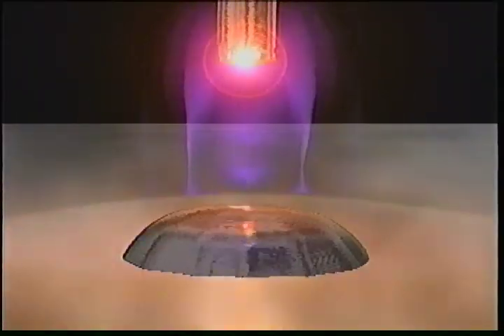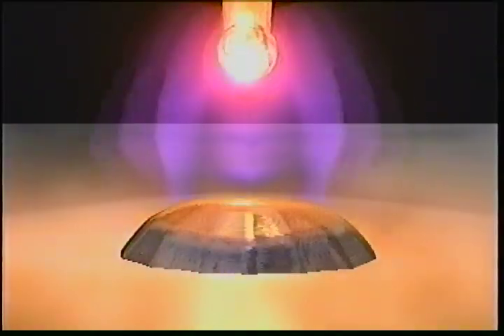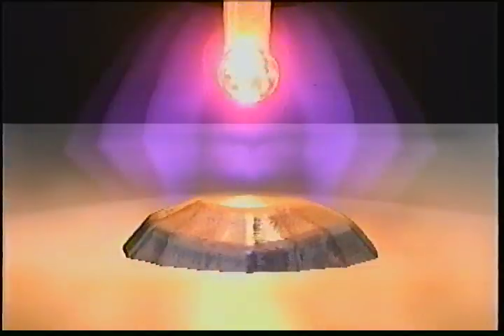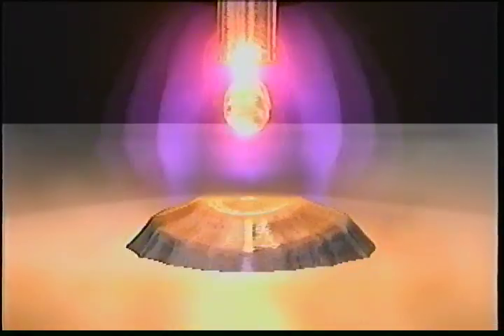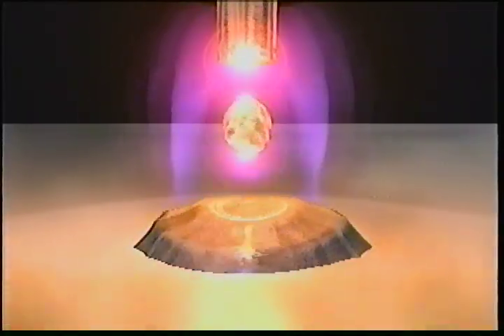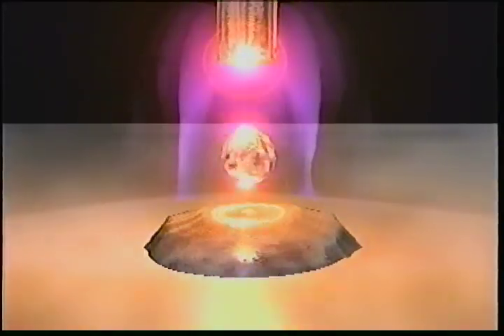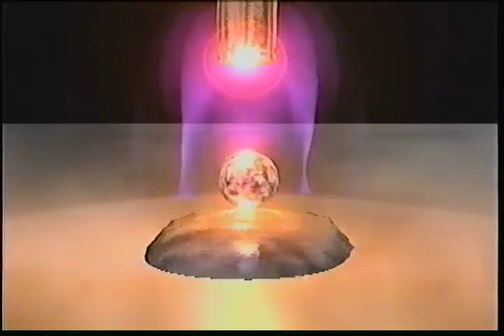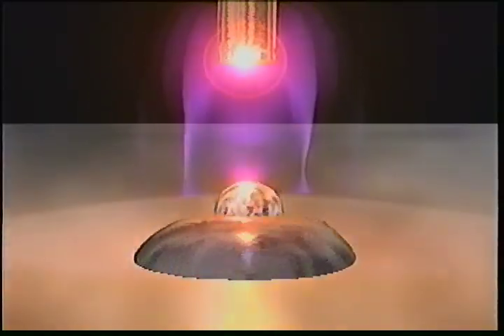Metal is transferred by the same method as spray transfer, except with pulsed spray transfer, the welding power source, through its electrical circuitry, rapidly changes the current output between a settable peak or high current level and a settable background or low current level. The current level never falls to zero, as it may during the short-circuiting or globular transfers. Instead, the background current remains at a level that will sustain an arc, but will not transfer metal.